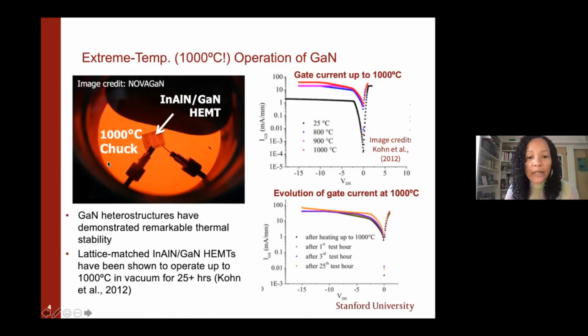And also something to note here is that the ambient is vacuum. So it actually doesn't capture a lot of the potential oxidation effects that you might encounter in some of the environments that I mentioned previously. So some of the work that we've done to advance this technology is study new operating environments that are oxidizing and also chemically corrosive. And so this is nonetheless really remarkable results showing, again, 1,000 degrees C operation, so gate current up to 1,000 degrees C, room temperature operation, and then cycling as well.